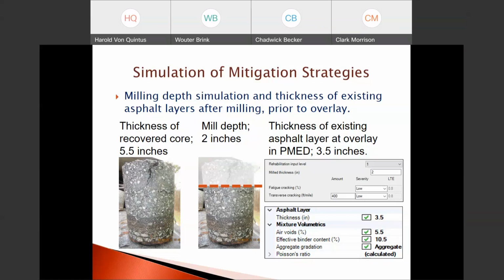Focusing on the middle block, you can see we have our fatigue cracking of a low severity, but the amount of cracking is not entered because this is rehabilitation input level 1, and we're having the program estimate the amount of fatigue cracking. Transverse cracking is from the distress surveys, 400 feet per mile, and those were rated as a low severity. And both of those get entered into Pavement ME.